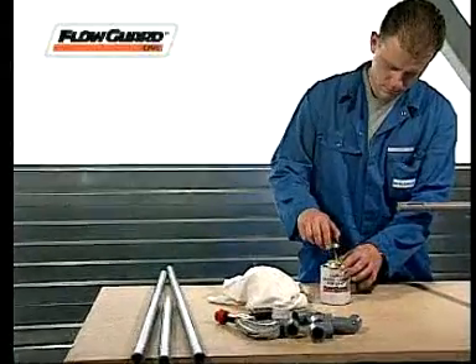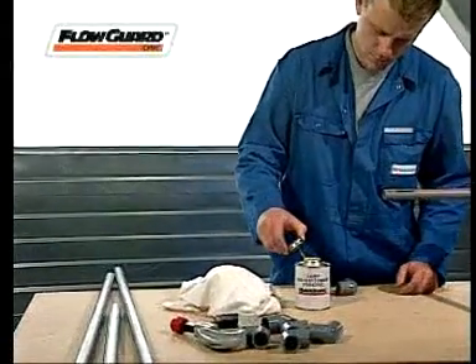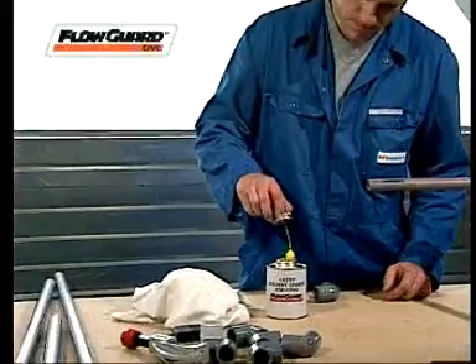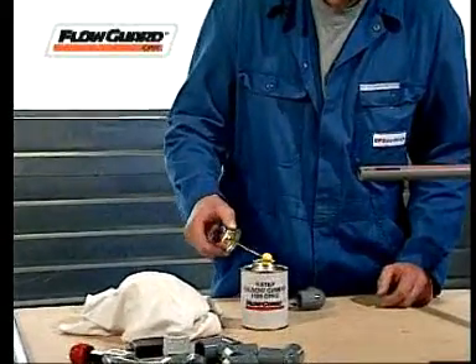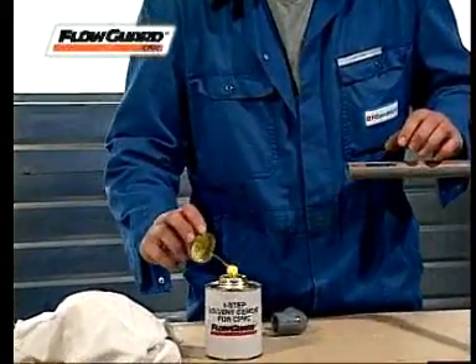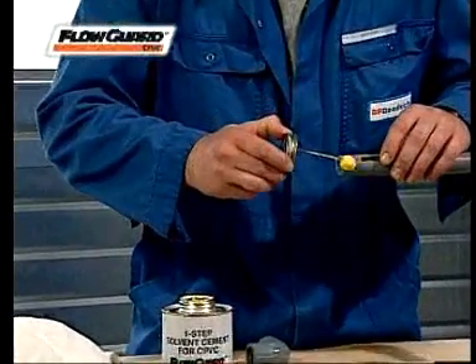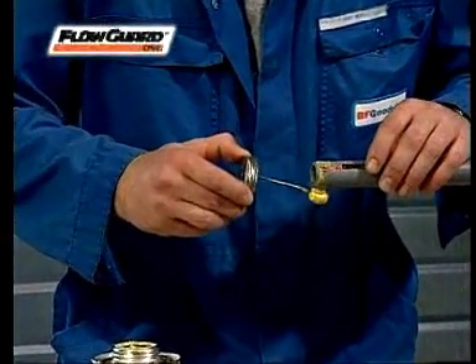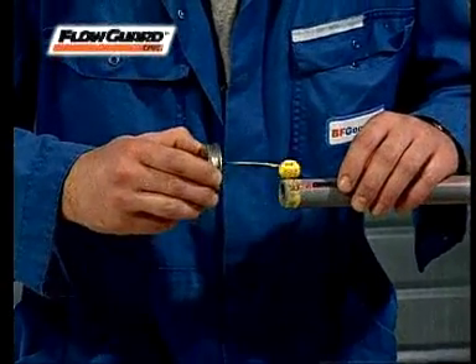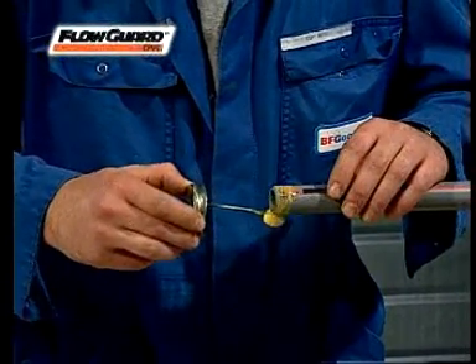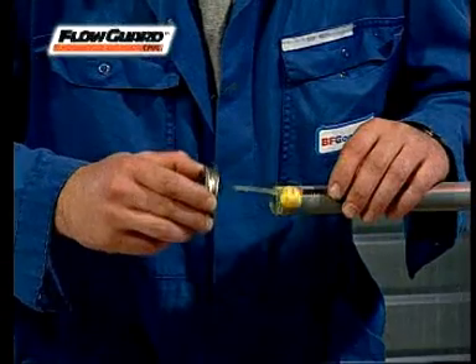The trick here is to remember to use enough cement. Most failed joints are the result of skimping on the cement. Make sure you get a nice even coating on the pipe over the entire surface which will go into the fitting. Note, in the two-step process, the primer is applied before the cement in exactly the same manner.